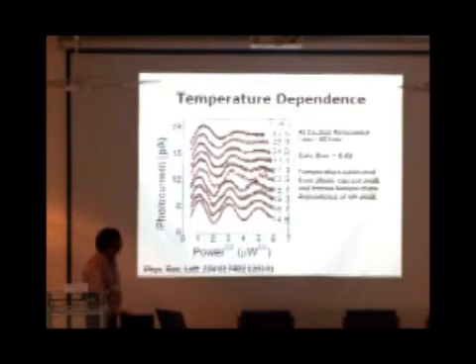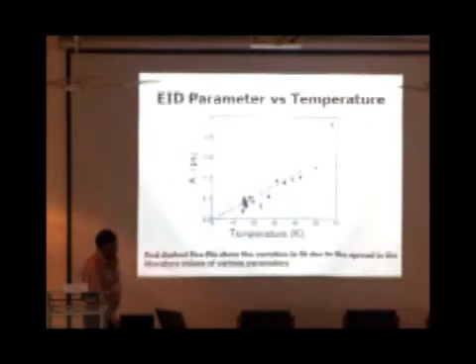So this is the main result. As a function of temperature, you measure the Rabi oscillations, and the red lines are the fits from which we estimate the EID parameter.